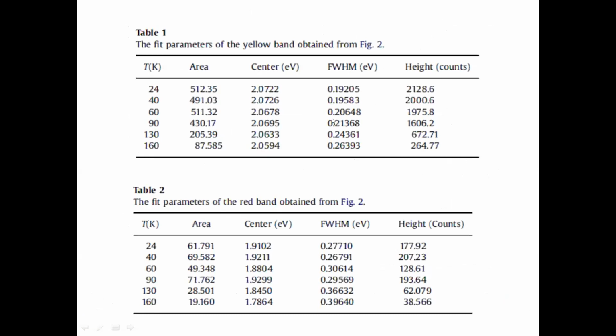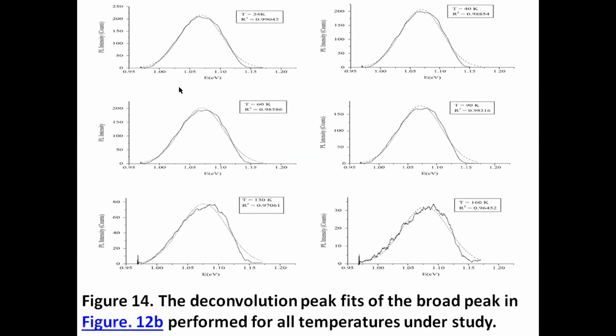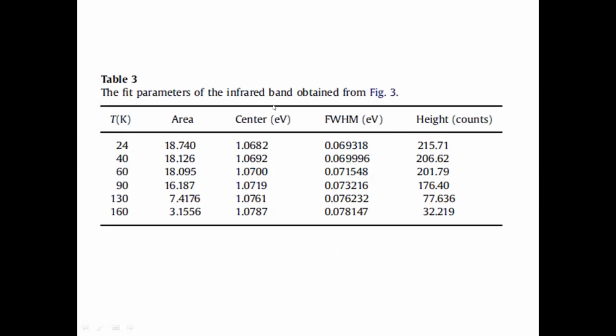Also, the same thing is done for the infrared band, where it was fitted to just one peak, and this is done for all temperatures. The fit parameters are also shown here for this infrared band: area, center, full width at half maximum, and height.